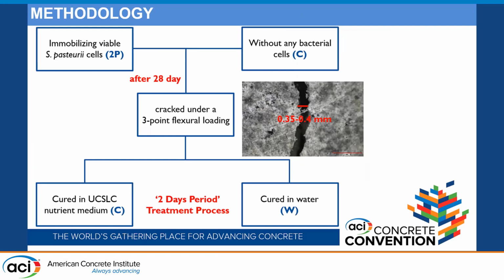For analyzing the self-healing ability of the natural minerals with bacteria cells, two different sets of samples were tested. The first is cement-based mortar in which bacteria cells are immobilized in the natural minerals, and the second is cement-based mortar including natural minerals without any bacteria cells. The samples were removed from the curing environment after 28 days and cracked under 3-point flexural loading, and 0.35 to 0.40 millimeter cracks were formed. We applied two different curing conditions. One set of cracked samples was cured in water, and another set was cured in nutrient medium, which again contained urea and calcium acetate. The curing process was done by submerging the samples in the curing solution for 2 days and leaving them at ambient conditions for 2 days.